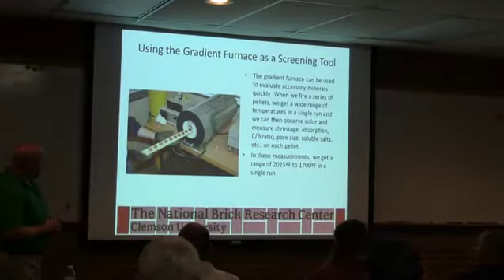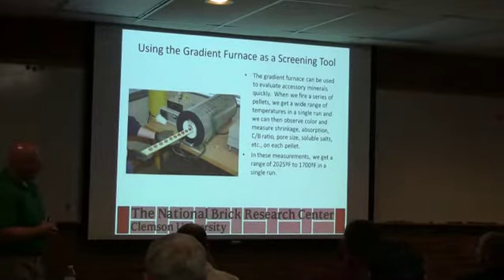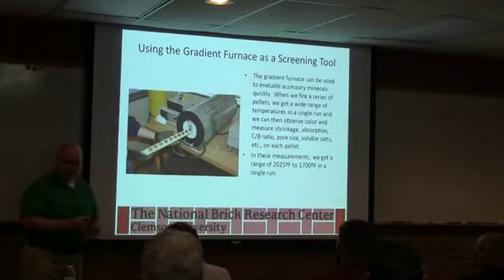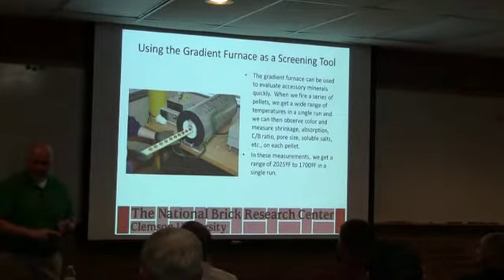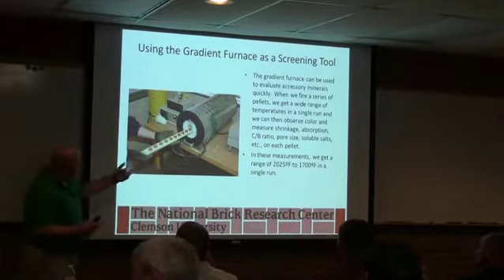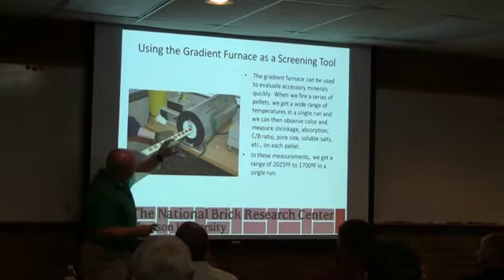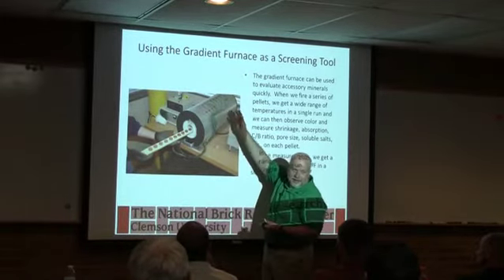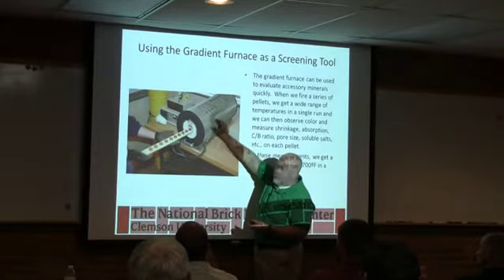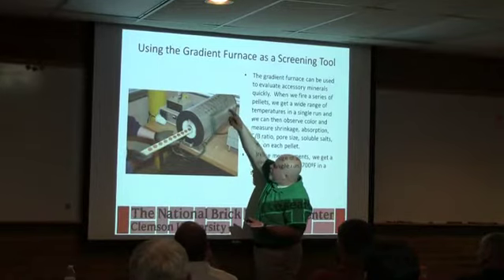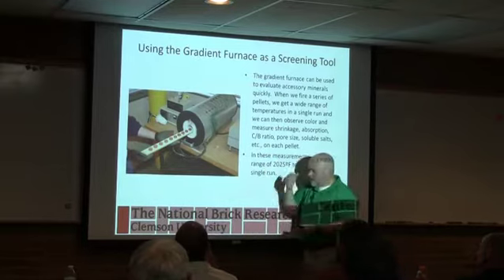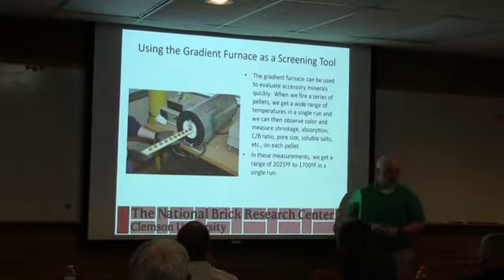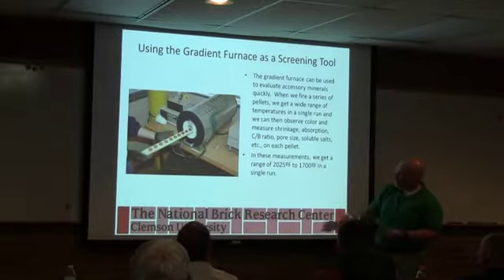One of the tools we use a lot is a screening tool. This is called a gradient furnace. Do you have a gradient furnace? You can either use it for color development, or some people will do a bar and fire the bar. The way it works is the winding is real tight at the back. It's a resistance furnace. Then the spacing between the winding spreads out as you come forward, so you get the hottest temperature in the back, and it's set up so that you get a steady decrease. I think we get about a 250 Fahrenheit range on ours, from the hottest to the coldest.